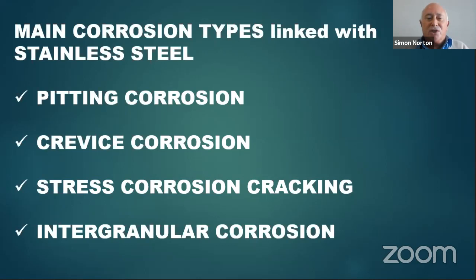Stainless steel is a strange material, unlike normal mild or carbon steel, which rust uniformly. And then, of course, when they are severely rusted, they spall and come to pieces. Stainless steel, particularly stainless steel piping, can be very, very deceptive. You will see no uniform corrosion. Suddenly a pit will develop, and when that happens, you can have catastrophic failure.